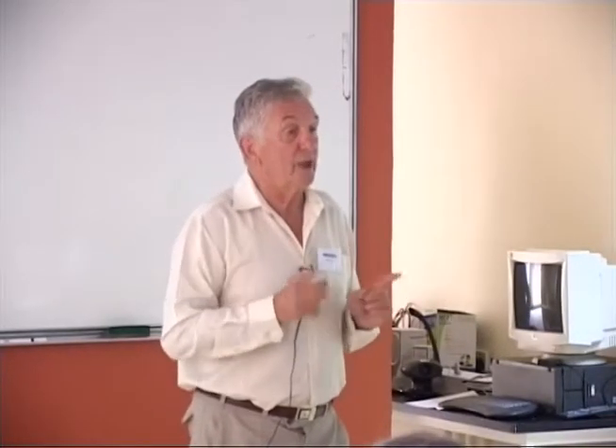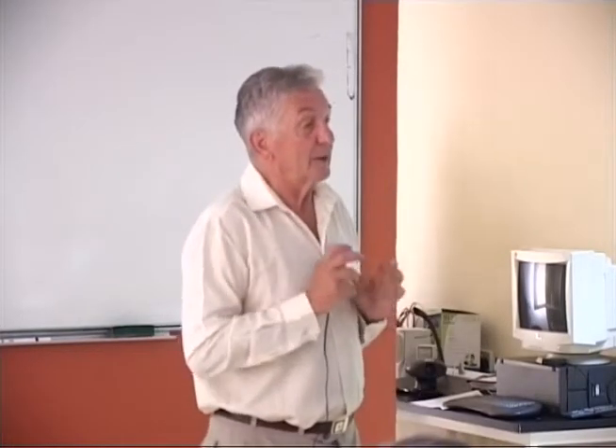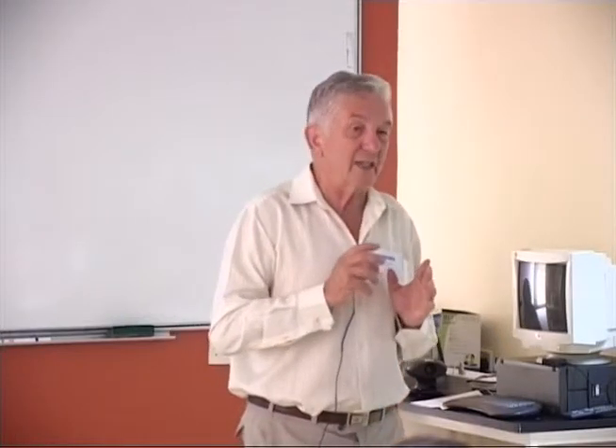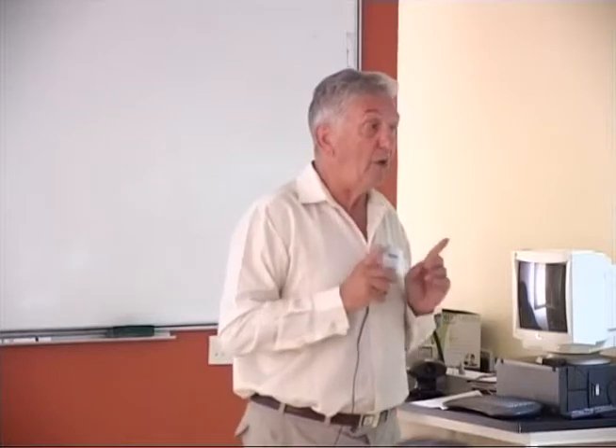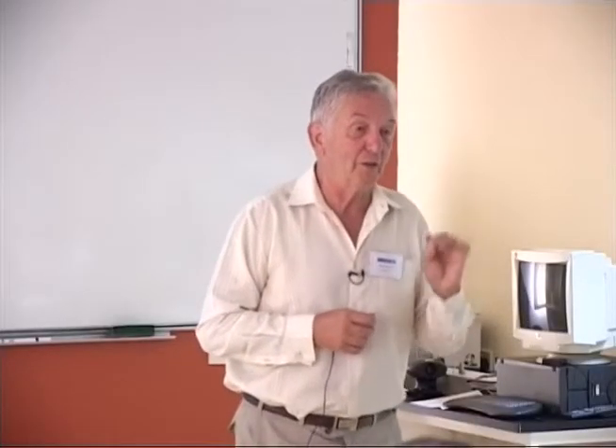What's the problem? Certainly it is a good process, but if you consider that such an industrial overlock sewing machine starts and stops so many times, it's very clear for everybody that no hydrodynamic lubrication is possible. Practically what we have is a kind of boundary lubrication, but we always have to consider some dry spells as well, because you cannot lubricate the parts abundantly. Otherwise you will have stains on the textile. The thread will be stained, so it's impossible to use a huge amount of oil. So you have to use just a drop of oil, which will cover the needs for lubrication. So this is one of the problems.